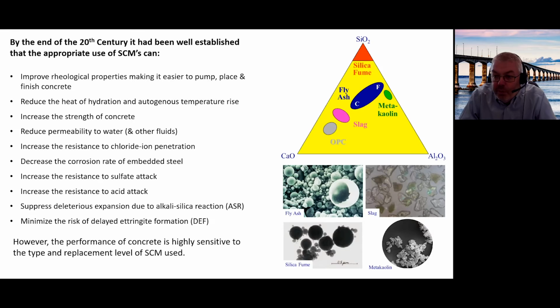DEF. However, what we've also learned is that the performance of concrete is highly sensitive to the type and replacement level of the SCM used. The SCMs that are widely used, if you look at fly ash, slag, silica fume, calcined clays like metakaolin, they're chemically very different from each other, and they are physically and mineralogically very different from each other. And therefore, careful consideration has to be given to how you use each one of these. And you can't immediately interchange and switch from one SCM to another. So it does require some careful engineering to take full advantage of all of these materials. So it's a happy story so far.